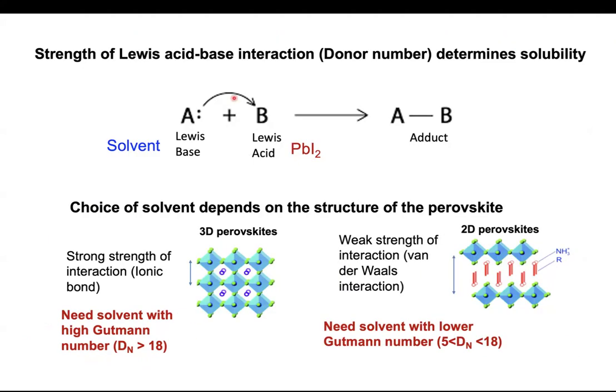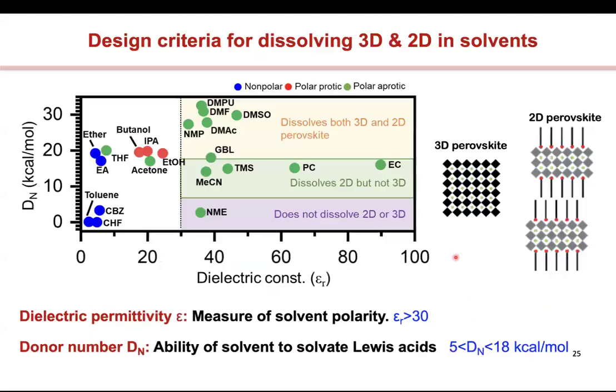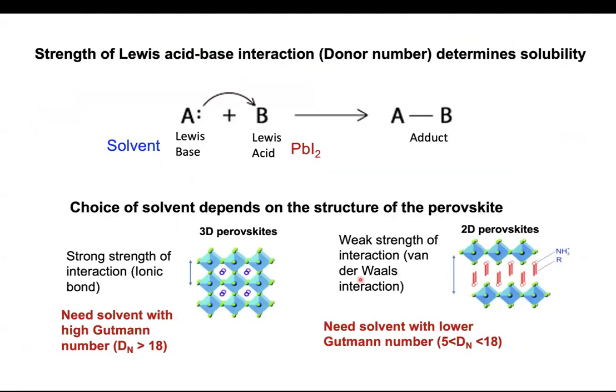Okay. But in comparison, you see the 2D perovskite, which is a layered structure. So I don't have this 3D network. In fact, I have a 2D network, and I have this organic here, which is this van der Waals gap. So which means that I can get away. I don't need a very strong solvent to dissolve this. And in fact, that's what we find. That's why we can get away with a solvent which has a slightly lower donor number in order to dissolve the 2D. Okay. And so I can do this with 5 to 18 and get something which is a 2D perovskite, which can dissolve in these solvents.